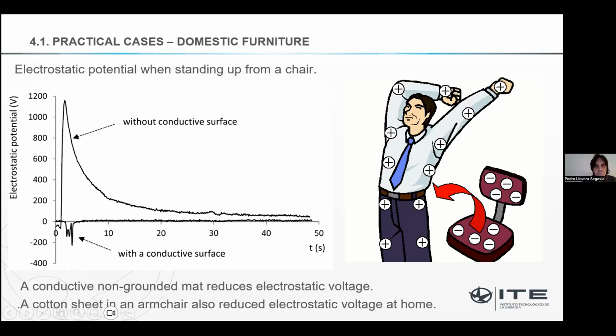Not a very important potential, but relatively high, with a very long discharge time constant, which depends on the shoes and the floor of these people. And we only put a conductive surface on the chair. There's a kind of conductive surface cell for making chairs anti-static with a grounding point, but we did not ground it, because grounding a chair in a home is really boring. It's annoying because you have a cable and you cannot move the chair. So just by making the surface conductive, the voltage becomes much less important.